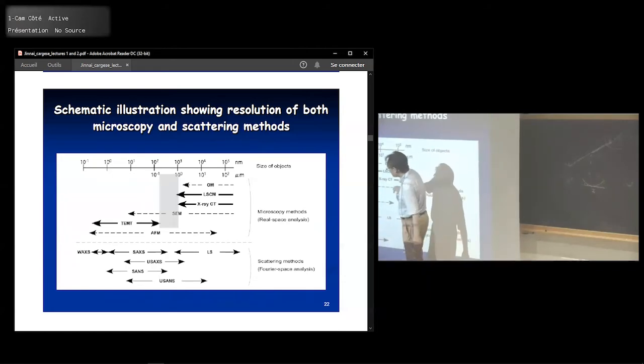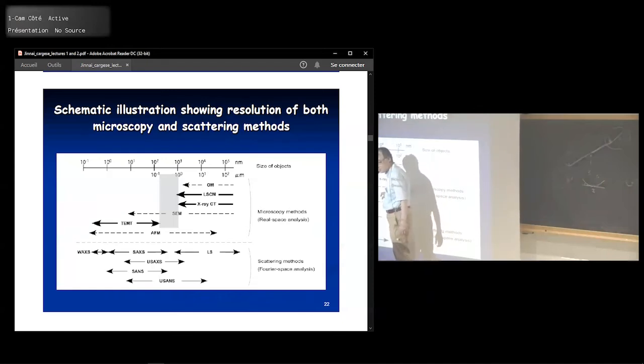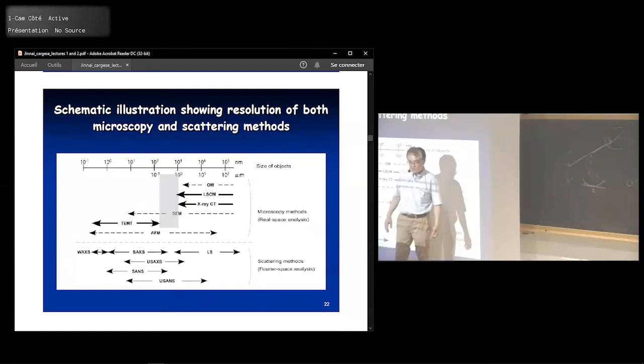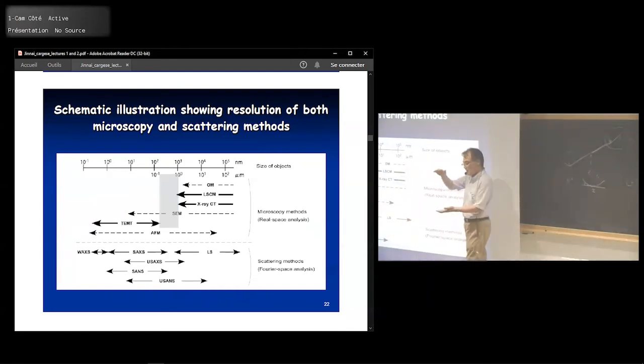Again, the different techniques, but before I draw TEM, this time it's a 3D TEM. The TEM comes somewhere here. It's a two-dimensional projection image, right? And 3D TEM, the 3D image, ends here, because for the 3D TEM you need a thicker sample than the normal one. The normal TEM, you probably need a thinner sample, like 100 nanometers thick or preferably thinner.